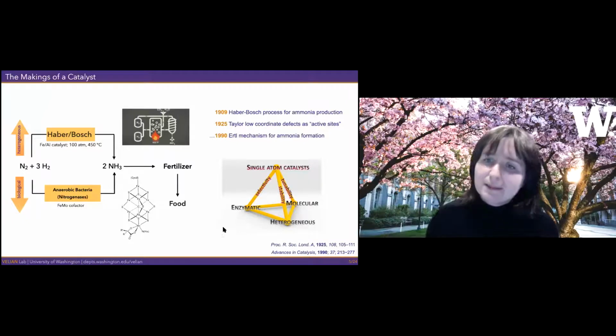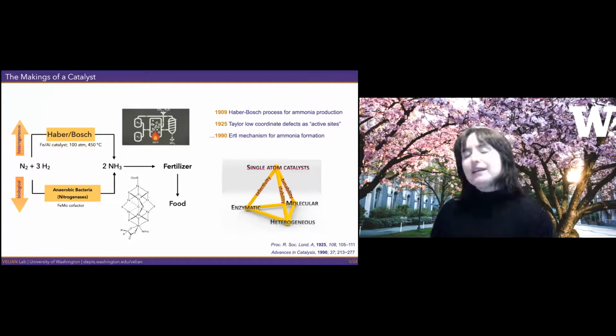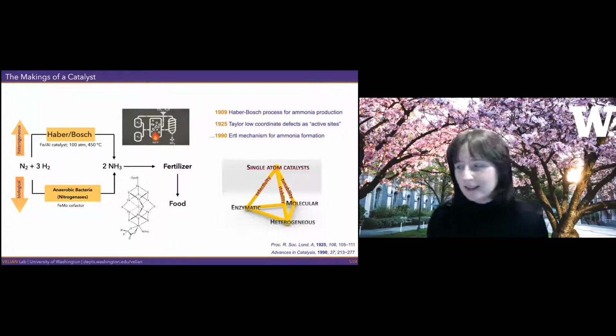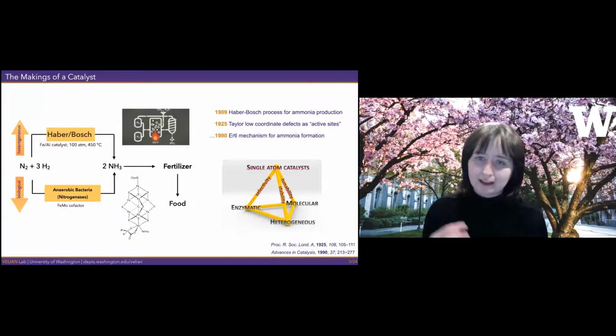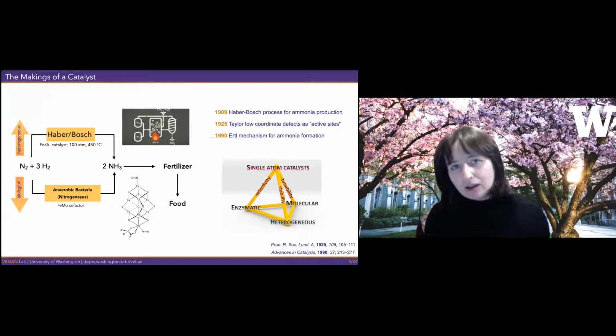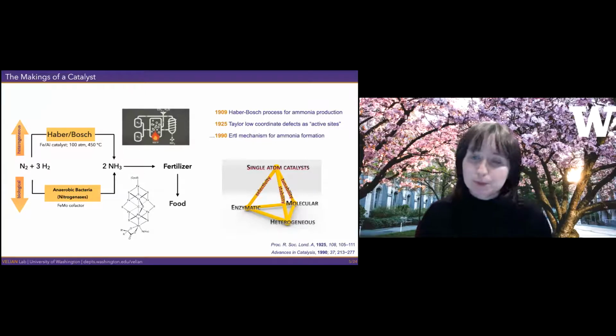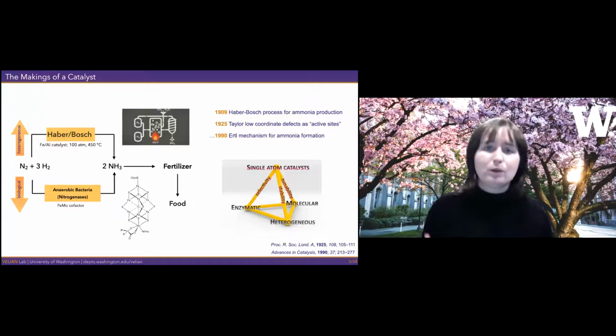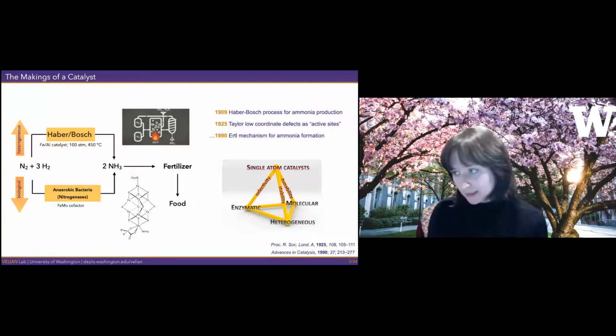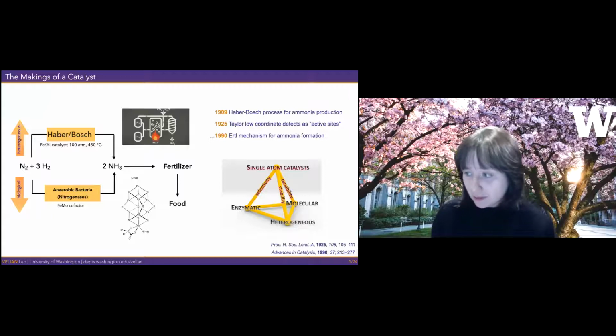And so this concept of active sites is really what it does. It reflects experimental evidence that many catalytic surfaces are not uniformly catalytic. So they have some special sites where atoms are distinguished by a special chemical coordination or composition, and they are the ones doing the work. And in fact, this was proposed by a chemist 100 years ago, well before there was significant experimental proof that that was the case. But of course, further studies showed that that was in fact true.